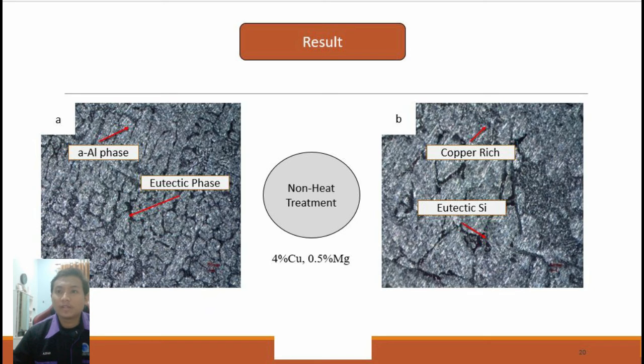For the microstructural study of the as-cast and heat-treated aluminum, copper, magnesium alloy, an optical microscope was used. So this is a sample of the structure captured under the optical microscope. The specimens were ground with emery paper of different grit sizes, such as 400, 600, 800, and 1200. We then polish with a polishing agent and etch for metallographic analysis. Based on the picture, the researchers found that the aluminum, copper, magnesium alloy examined has a dendritic cell structure. We can see that the as-cast micrograph consists of aluminum solid dendrites as the primary phase in grey color, with the interdendritic space filled by eutectic mixture.